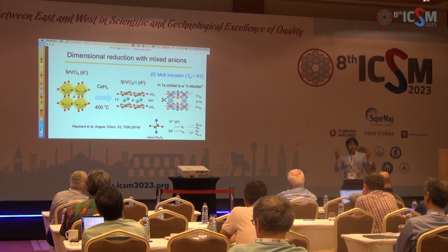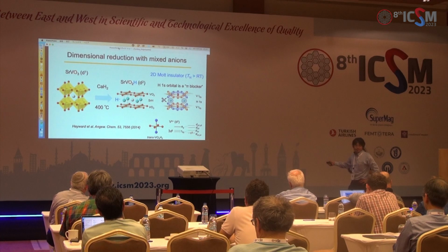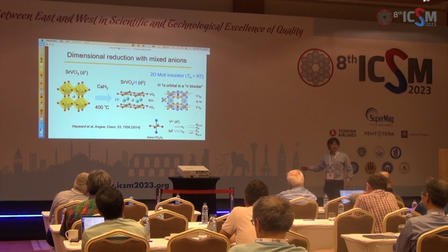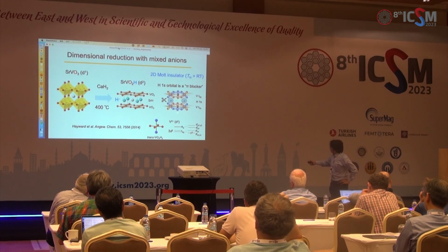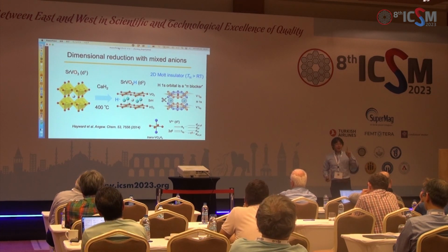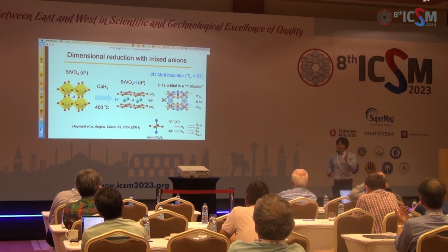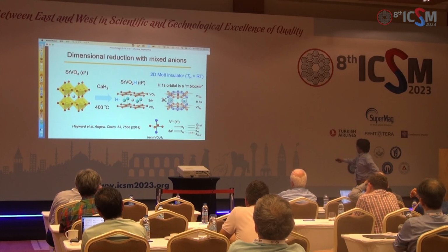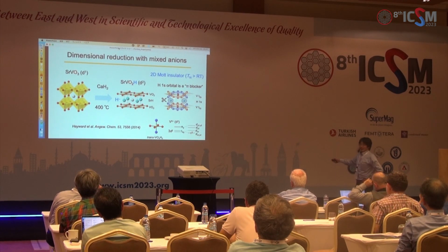So now, concerning the bondings or maybe magnetic interactions, you have to consider these dxy and dyz orbitals, as you can see here. Then along the ab plane, the vanadium O2 plane, you see that there is pi bonding. So the bonding interactions exist in these vanadium O2 planes. In contrast, along the c direction, this t2g orbital is orthogonal with the hydrogen 1s orbital. Actually, hydrogen doesn't have a p orbital. So the lack of p orbital enhances two-dimensionality. So effectively there is no interaction.